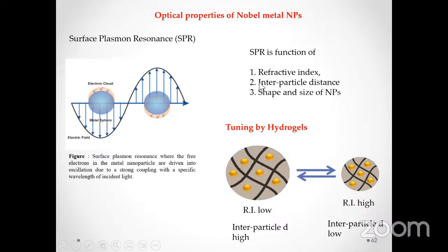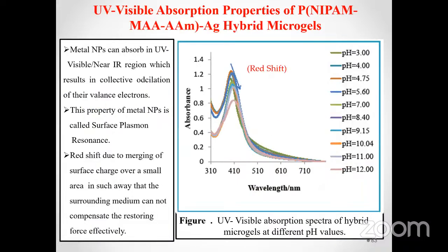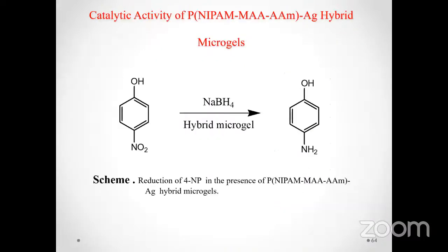When the interparticle distance is decreased, then the surface plasmon resonance effect is changed. This change appears in the form of a change in absorption intensity, or in the form of a change in lambda max, as can be seen in this figure. As we have increased the pH, a red shift in the lambda max was observed. And it shows that this system can be used as a tunable optical system.